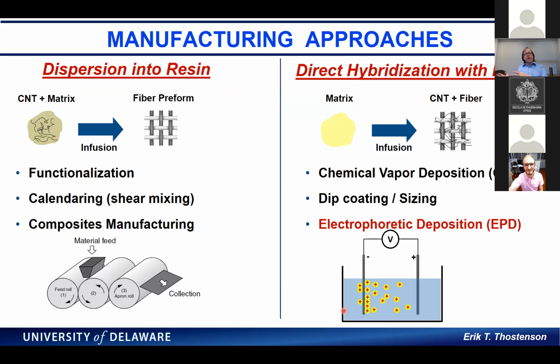The other approach is direct hybridization with fibers, basically integrating the nanomaterials together with the fibers, followed by infusion. And there are a couple different ways we've done this in my group, and there are other ways that other people have developed. But I think the three that are most common are chemical vapor deposition, dip coating and sizing, and something we spent a lot of time on in my group over the past several years is electrophoretic deposition.